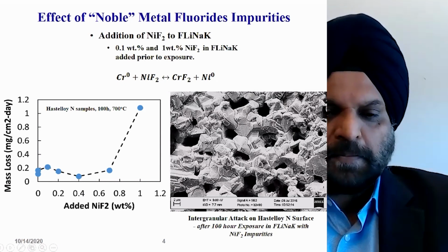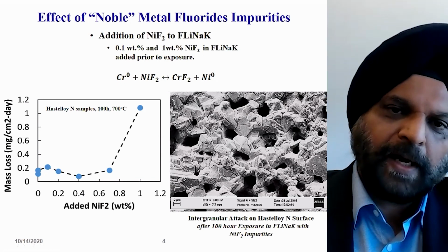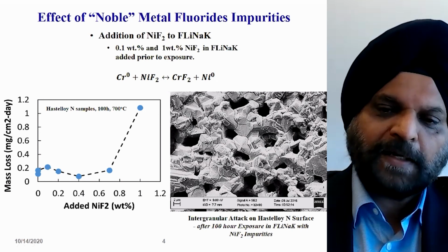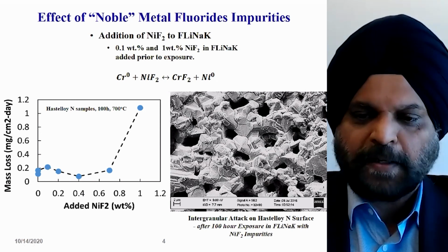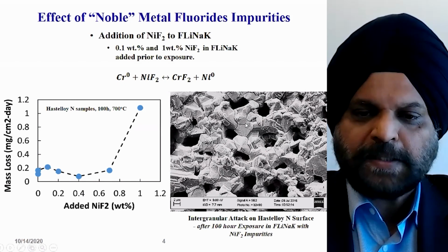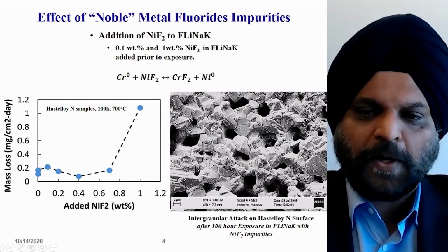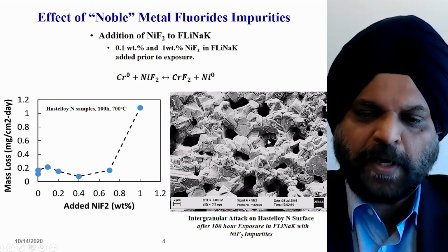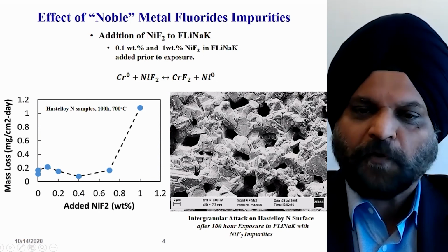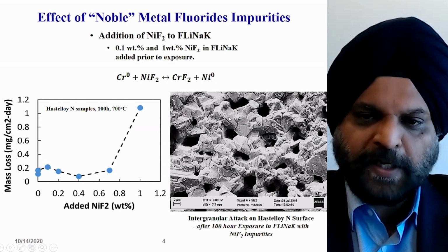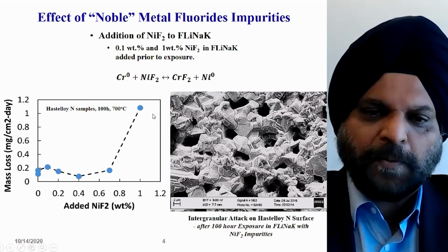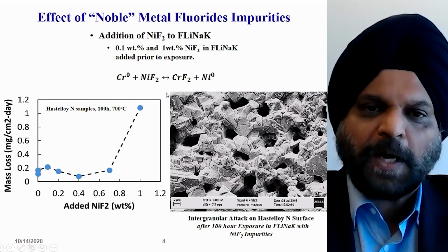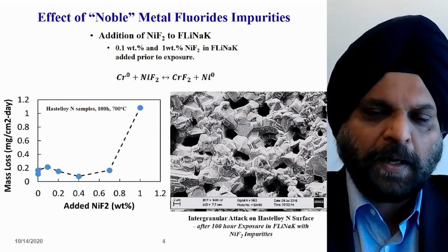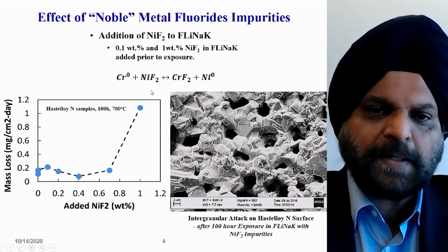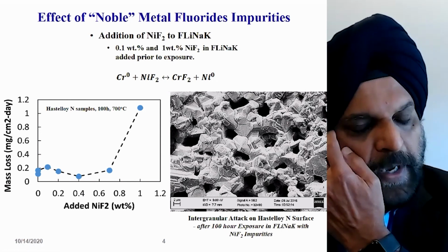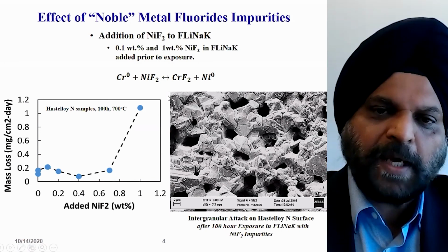If you actually have a lot of this nickel fluoride impurity, it can lead to very aggressive attack. In 100 hours at 700 degrees Celsius, this Hastelloy N lost grains from the surface because of intergranular attack. You can see that grains just fall off because of the aggressive attack. Obviously we hope we will never have this amount of impurities, but what we are trying to do is understand, under extreme cases, what degradation mechanisms can operate.